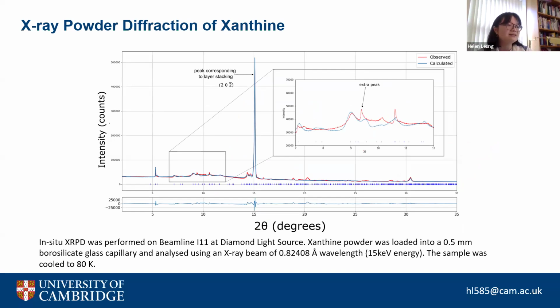And unfortunately, with just the Form 1 model, we struggled to really model this data very well. You can see in the little blow up that I've got here on the slide, there's an extra peak that we couldn't really account for. The peak shapes were asymmetrical. They all seem to have some sort of right sloping shoulder. Just purely having the CIF for Form 1 xanthine didn't seem to be able to account for everything that we were seeing in the XRPD.